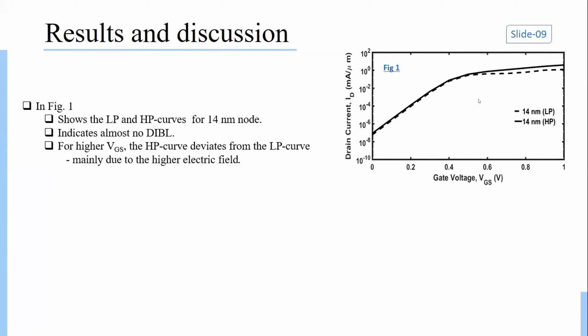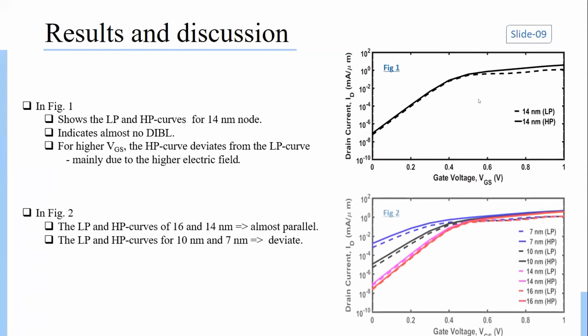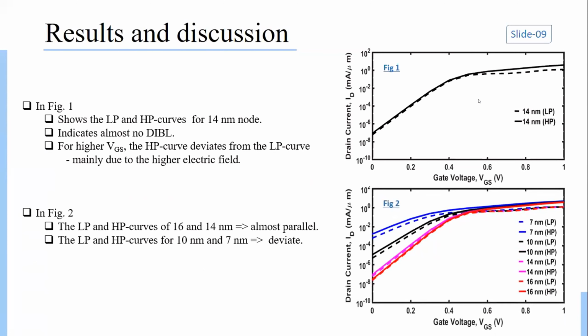Now from figure 1, as both the transfer characteristics curves for HP bias and LP bias are almost parallel, there is almost no DIBL effect in figure 1. For higher VGS, the HP curve deviates from the LP curves, mainly due to the higher electric field. From figure 2, the LP and HP curves of 16 nanometer and 14 nanometer are almost parallel, but when channel length shrinks more, SCE dominates slightly and thus the curves deviate. We will see the effect of DIBL in the DIBL analysis part.